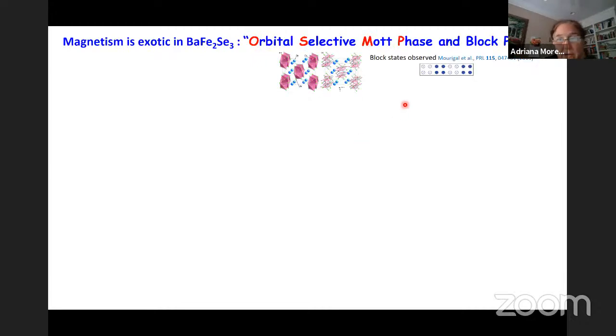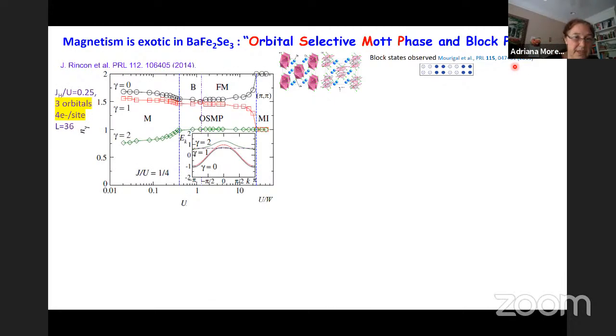From the experimental point of view, I already told you about this material, barium iron selenide, which has iron ladders and this structure with ferromagnetic blocks ordered antiferromagnetically. These are neutron scattering results obtained by Mourigal in 2015. Interestingly, these are results that our group calculated in 2014, where we studied the 3-orbital model with 4 electrons.